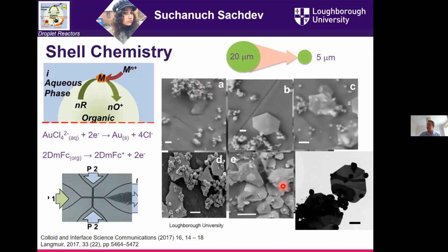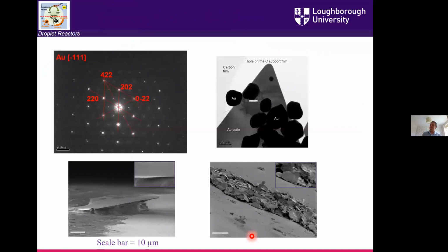It wasn't always perfect. So you can see there are some smaller spherical particles amongst these bigger platelets in this. But it was incredibly interesting to find that we could really tune the morphology and the shapes of these by just simply changing the droplet size. We hadn't even gone on to any fancy chemistry yet by adding ligands in there, and we were getting wonderfully different particles. Those platelets of gold were wonderfully crystalline, and in some cases when we put them under the TEM would simply dissolve and melt away. They're only 90 nanometers thick, but microns in size, single crystals.